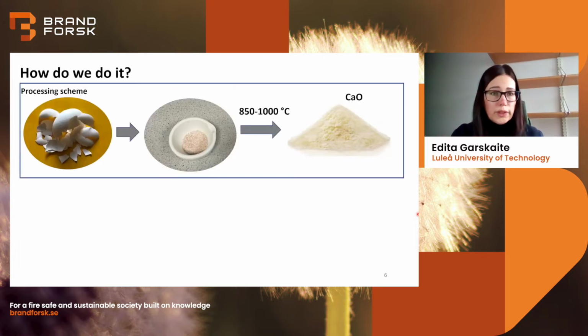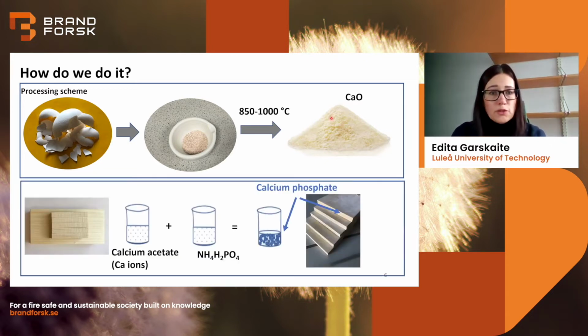So how do we do it? Firstly, here is a very simplified processing scheme. We take eggshells, we grind them, and then we anneal at different temperatures. At high temperatures, annealing is supposed to give us calcium oxide. Then from this calcium oxide, we make calcium acetate. And that calcium acetate, which is dissolvable in water, gives us one solution.